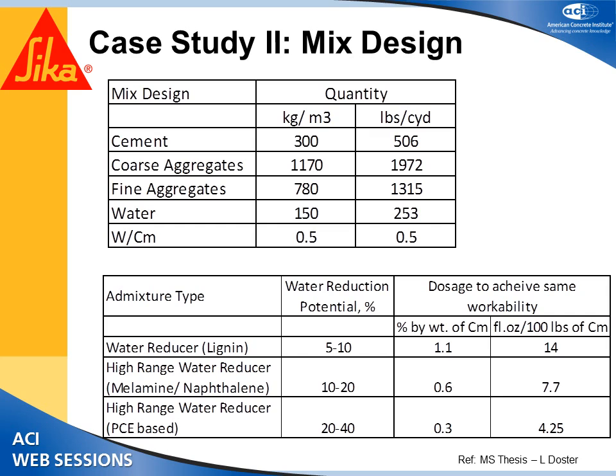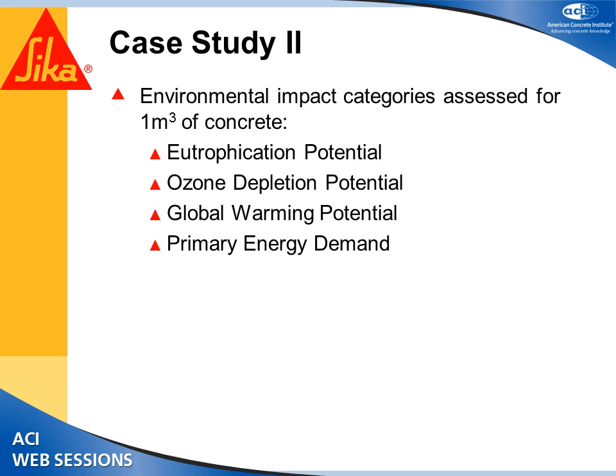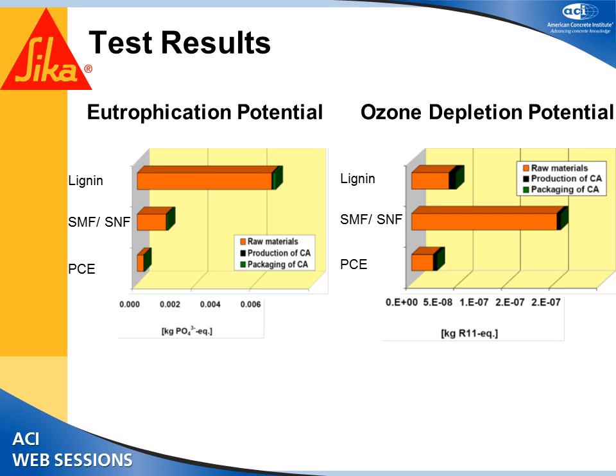For the lignin admixture, he had to add 14 ounces to achieve the same slump. For the naphthalene melamine, he had to add 7.7 fluid ounces, and for the PCE, he had to add 4.25. And he ran LCA on all these 3 mixes. The impact categories he looked at were these 4: eutrophication potential, ozone depletion potential, global warming, and primary energy demand. And the results were as follows. For the eutrophication potential, over here you see this was for the lignin admixture, this is for the SNF and melamine combination, and this was for the PCE.